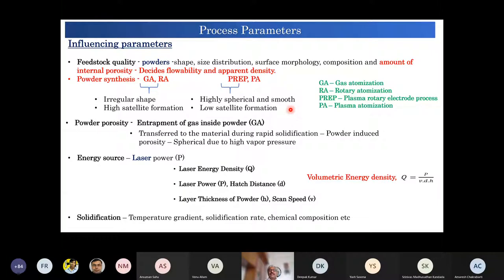Then another important parameter is the energy source, that is, in the process, laser power, laser energy density, hatch distance, layer thickness of the powder, and scan speed. All these things are important, and overall volumetric energy density is a function of all. It is given by laser power divided by the scan speed times hatch distance times the layer thickness of the powder. So this gives you volumetric energy density, and this serves as an important parameter in deciding many things.